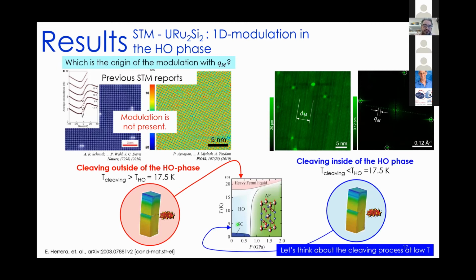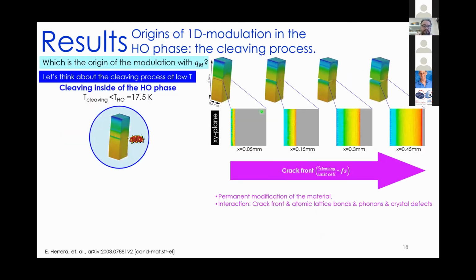This led us to think about the cleaving process at low temperature. To analyze this main difference, we simulate what happens when we cleave a sample. Cleaving a hard single crystal is a fast procedure by which the bonds are broken first on one side of the sample, and then the crack front travels through the sample in a very short amount of time. In our case, we calculate that the time is around some femtoseconds.